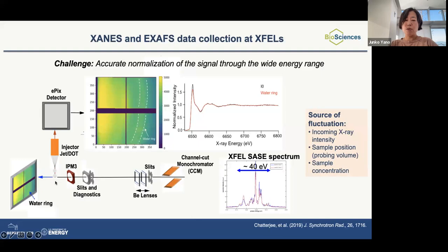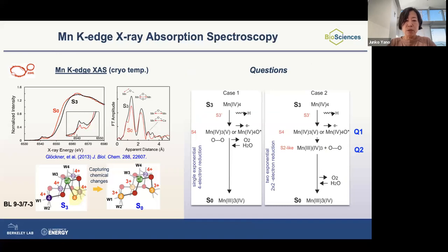And then if you were to use, particularly, a liquid jet, if it's not a stable high flow jet, the probing volume will be fluctuating quite a lot. So how do we deal with these kinds of multiple fluctuations? We decided to use a scattering detector at the downstream. So this scattering intensity includes the incoming X-ray fluctuation as well as the probing volume fluctuation. So by using this, we can normalize the data through the XFEL region quite well. So that's what we're doing.